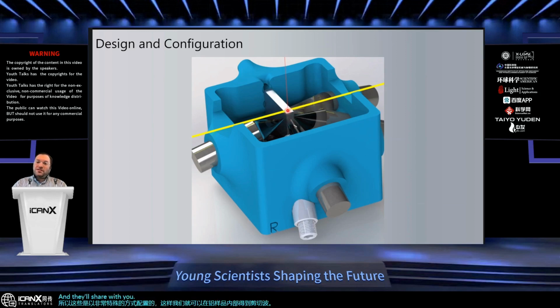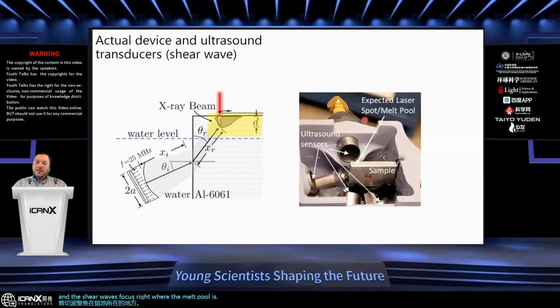And those shear waves focus right where the melt pool is. Okay. And this is the actual device that we use. This is after the water was drained. You can see the ultrasonic sensors around here, and they're all targeting a melt pool on the surface, about 200 microns beneath the surface on the sample.